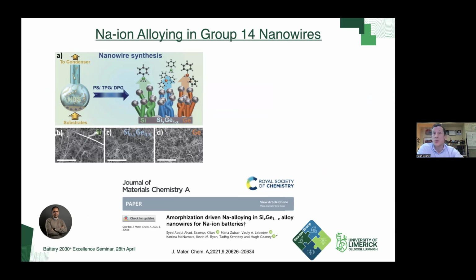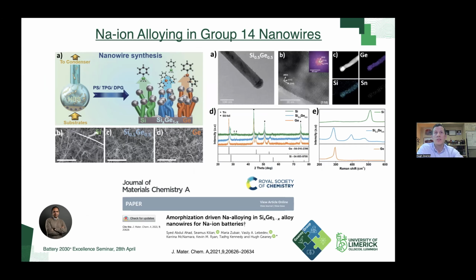As I mentioned, for sodium ion, it's more difficult to get these lighter elements in group 14, silicon in particular, to reversibly cycle. So we did some basic analysis of our nanowires. We have pure germanium here, we have our pure silicon here, and we confirmed that we made this nice 50-50 alloy in between.